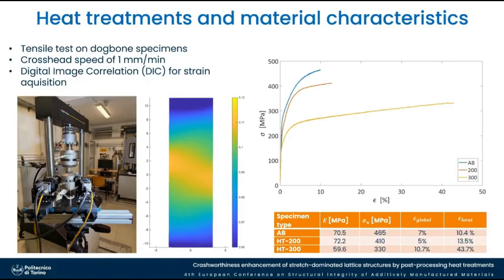And here we report the results in terms of true stress and true strain, where the strains are computed where we have the necking. You see that there is a significant difference between the as-built, 200 degrees and 300 degrees treatments. Basically, increasing the temperature, we have an increase of the ultimate strain and a consistent decrease of the ultimate stress.